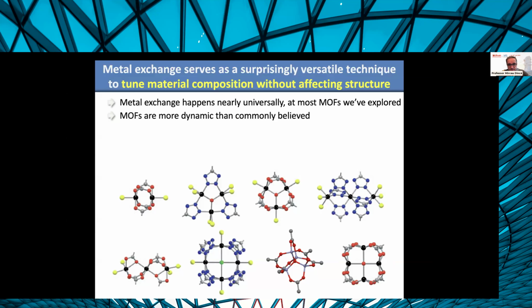All I need to do is actually just make the initial MOF, make the parent MOF from whichever metal it likes to be made from, and then exchange that metal with something else, with titanium or chromium or whatever I like for my catalysis or desired reaction. So basically, this opens up in a very rational way, because I know exactly what the structure will be, a huge compositional space and a huge sort of framework for studying reactivity and catalysis with these materials.